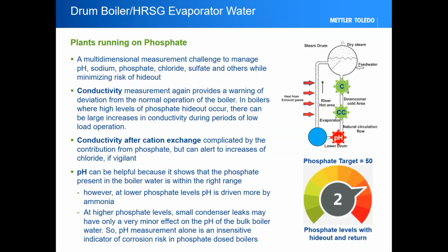Now, phosphate, back to phosphate. If you're running phosphate, you don't need an analyzer, but it's a heck of a lot more convenient because you're really trying to address a multi-dimensional problem, using conductivity, cation conductivity, and pH. But based on the dosing levels, at lower phosphate levels, the pH is going to be driven more by ammonia. At higher phosphate levels, small condenser leaks might not even be noticed based on pH. So pH alone is not a very accurate or very reliable tool in your toolbox. Really, direct measurement of phosphate, either taking grab samples back to the lab or with an online analyzer, is a much better way to go to really avoid the headaches of the phosphate hideout and return that this little graphic is highlighting.